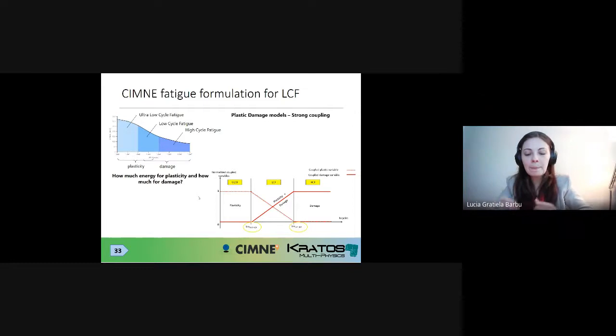Why is it needed? You see, when you have a plastic damage model which is exhibiting weak coupling, what you have is a basic plasticity model, and you compute the damage variable based on the level of plastic strain that you have in your model. And this is very good. It's very useful for a specific range of application.